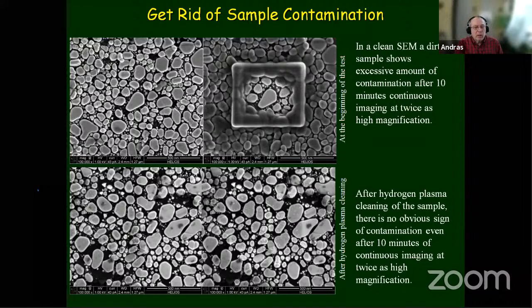The sample had contamination precursor molecules in it. The SEM itself was clean. So after cleaning the sample in hydrogen plasma, obviously in a gold on carbon sample you will not clean in oxygen because it will just crumble. You can see that after cleaning, the first image looks a little bit different, but after 10 minutes, you don't see that ugly contamination because the precursor molecules were largely removed from the sample. Next slide, please.